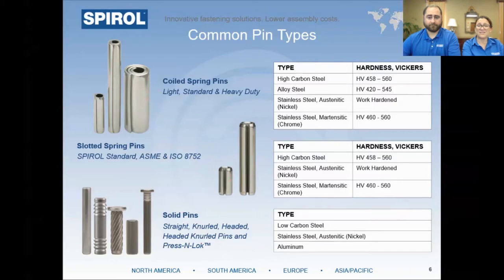However, it's not heat treated and therefore not recommended for use in hardened holes or in applications where the pin is subject to dynamic loading, as it will work harden. And this is particularly true for 300 series stainless slotted spring pins, since most of the stress is concentrated 180 degrees from the slot. In general, we actually wouldn't recommend a 300 series slotted pin due to the inherent design limitations of this type of spring pin. 420 stainless steel, sometimes referred to as martensitic stainless, provides good corrosion resistance in most common atmospheric and environmental conditions in the presence of free oxygen. 420 stainless is heat treated and has mechanical properties similar to high carbon steel with the enhanced corrosion protection.